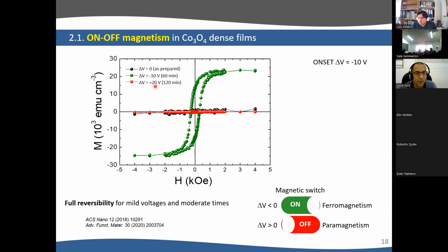Then interestingly, if you apply, for example, 20 volt for 2 hours, we remove all this ferromagnetic response. So effectively, we're able to switch on and then switch off the ferromagnetic signal of this layer in the same way as you would switch on and off the light of a lamp, for example, or a computer. So we call this magnetic switch, voltage-driven magnetic switch. Now you can see here this is slow, that you need relatively high voltage and so on. So the next slides are to further understand what happens and to try to make things faster.